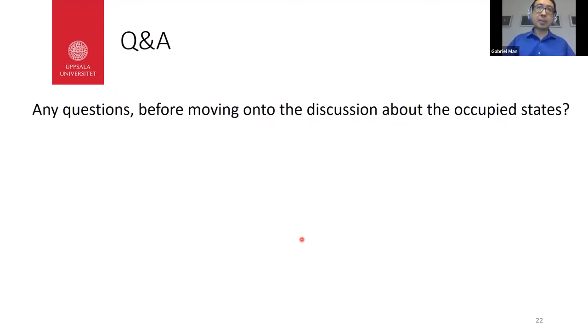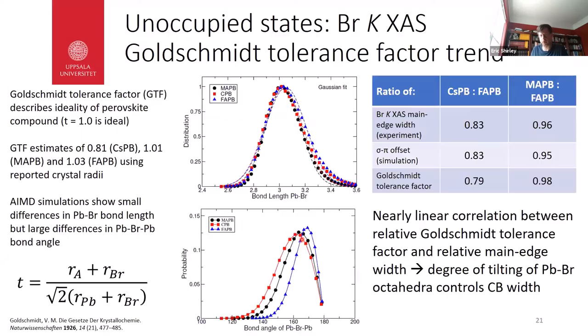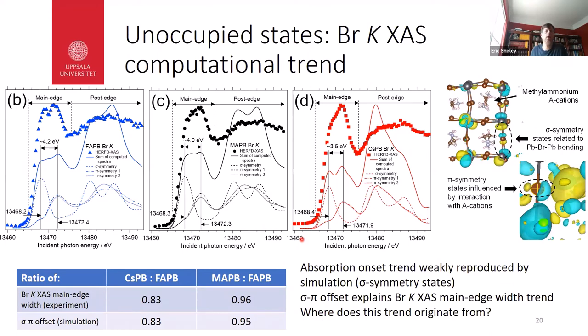Yeah. In sulfur compounds, including molybdenum disulfide and some others, you can have a second band gap within the unoccupied states above a first group of bands. I'm wondering, your spectra have states that seem awfully split off from the ones higher up. Do you think there's any evidence of a second band gap that maybe is not resolved because the core edges are quite broad, even with the high resolution? Yeah, I see what you're saying. I suspect not, because I've seen the unbroadened versions of the simulated sigma and pi symmetry states, and they don't seem to suggest that there is a second band gap.